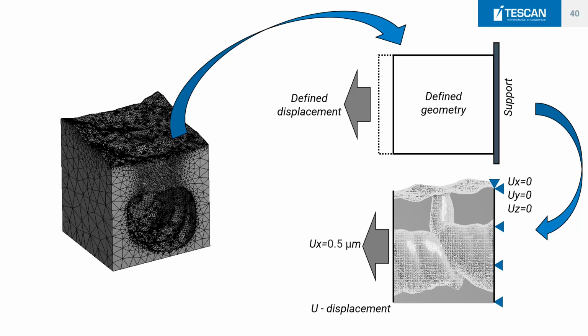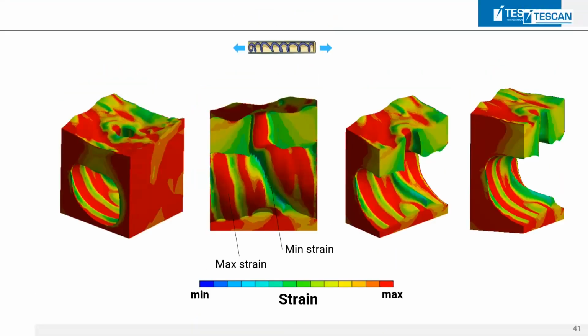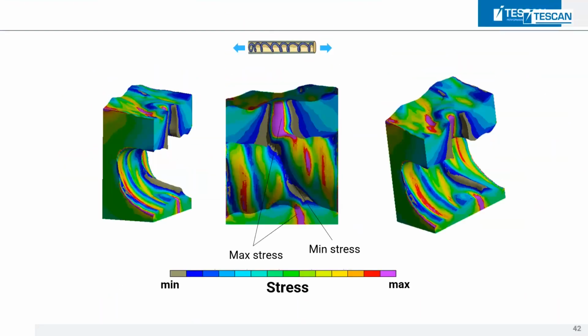So we quickly did a finite element modeling of such a structure. We used this reconstruction, meshed it, and added basic properties to it. We defined the geometry, the displacement, and all the conditions, and we observed how the strain develops. And you could see that in the spiral thickening you have minimum strains, and in the cell wall you have maximum strains. So it seems that under tension, the spiral thickening really works as a support. That's also reflected in the stress: the spiral thickening has a minimum stress, while the cell wall has the maximum stress. Of course, there is a pit, and the biggest stress was in the pit, which here could be seen as a defect in the wood.